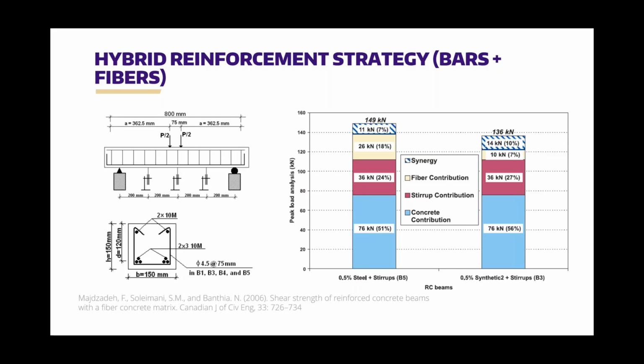You can see there's both a test series that was done with steel fibers and a test series that was done with synthetic fibers. So we'll look at the bars on the right. And the quite curious thing about all of this is you can see the fibers have some small contributions, not as large as if it was steel fibers, but there's this interesting box at the top there, which is that hatched region, which they named synergy, which is really just the extra strength that you saw in the beam with both fibers and transverse reinforcement that wasn't accounted for by the strengths of the other beams that didn't contain both. And so that's what we're really trying to look at in this series of tests and this investigation.